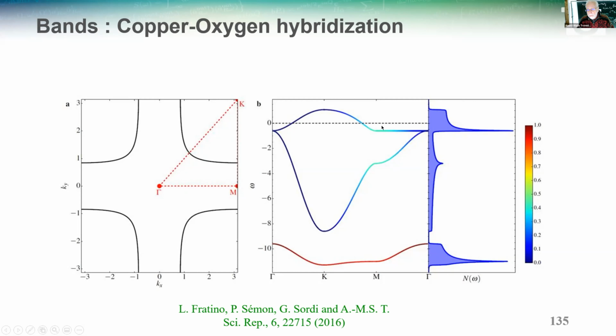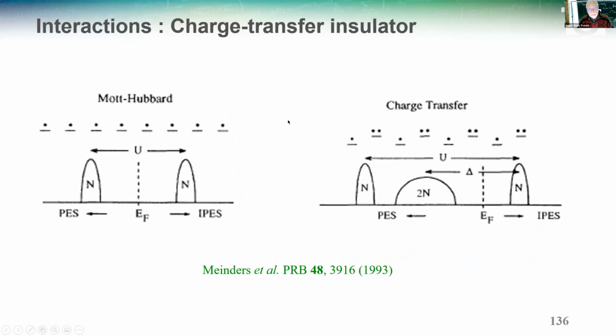And if you focus on the band near the Fermi energy, which is this dashed line, then you see regions that are neither blue nor red. So it means that copper and oxygen are strongly hybridized. And that's why Anderson proposed the one-band Hubbard model.